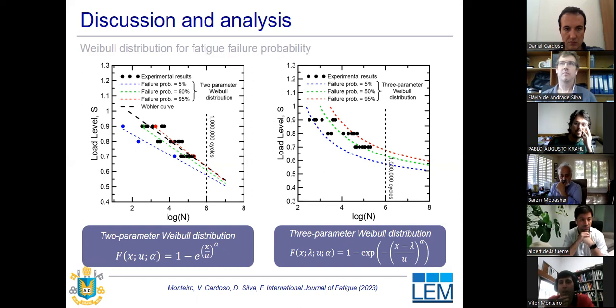For a two-parameter Weibull distribution, we can reach a line based on a failure probability. And for the three-parameter, we can have a nonlinear curve with an asymptotic behavior reaching the 0.50 load level for this distribution.